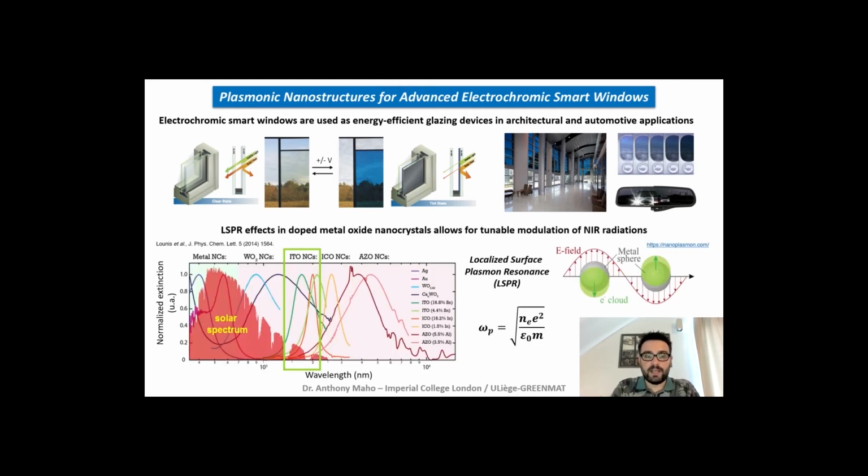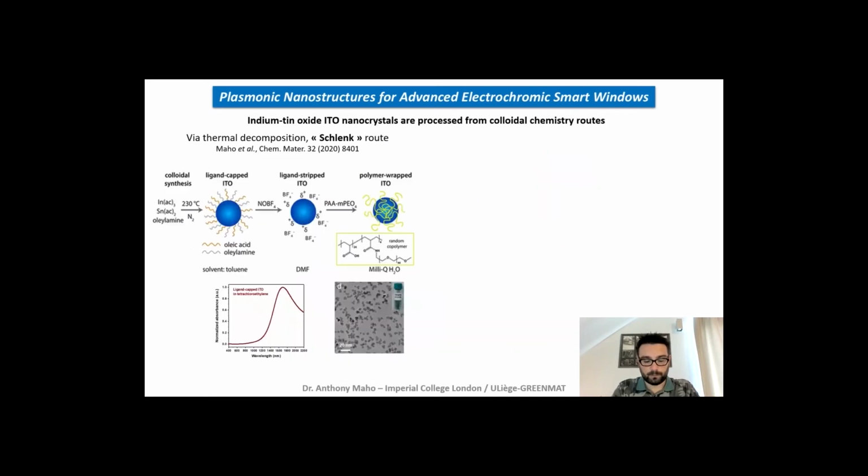Particularly, the idea here is to exploit the properties of localized surface plasmon resonance, LSPR, demonstrated by specific nanocrystals of highly doped metal oxide for inducing intense and selective light absorption behavior at specific wavelengths, typically in the near infrared, when considering species of, for instance, aluminum-doped zinc oxide or indium tin oxide in view of their carrier charge concentration.